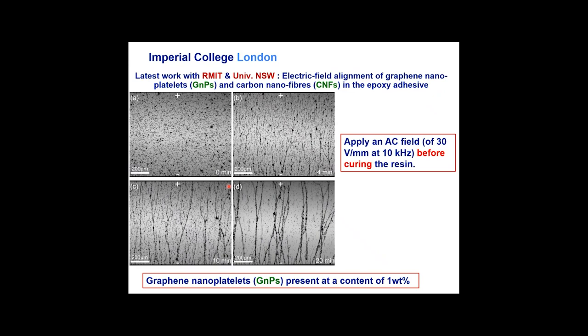More recently, in work with RMIT and the University of New South Wales and friends and colleagues there, we've been looking at using graphene nanoplatelets and carbon nanofibers to actually toughen the adhesive. Further, what we've done is actually align the materials inside the adhesive layer. Now this shows work for graphene nanoplatelets at 1%. It's successive time frame, 0 minutes, 4 minutes, 10 minutes, 20 minutes. Here would be one carbon fiber reinforced plastic CFRP substrate. We're gluing together CFRP. Here would be the second CFRP substrate.